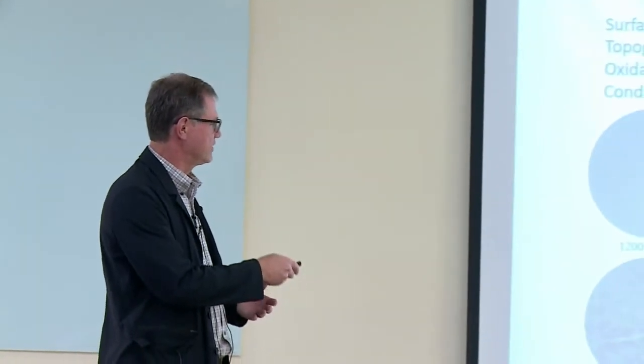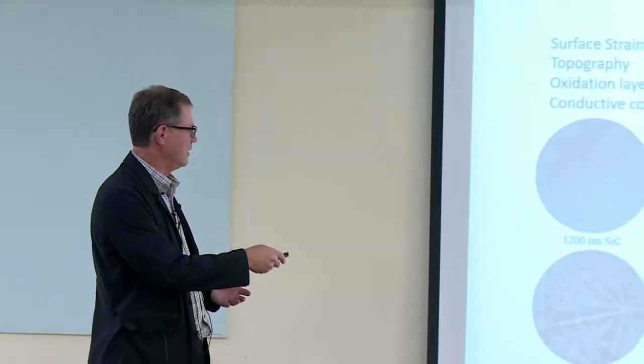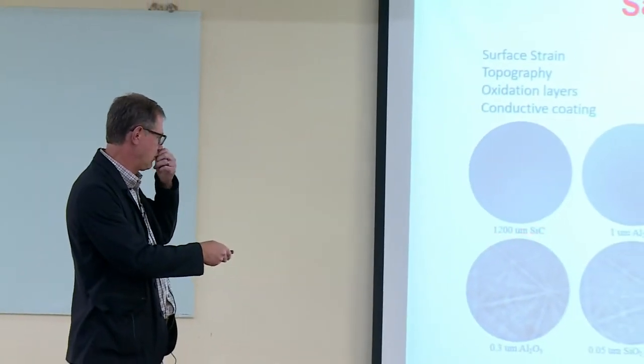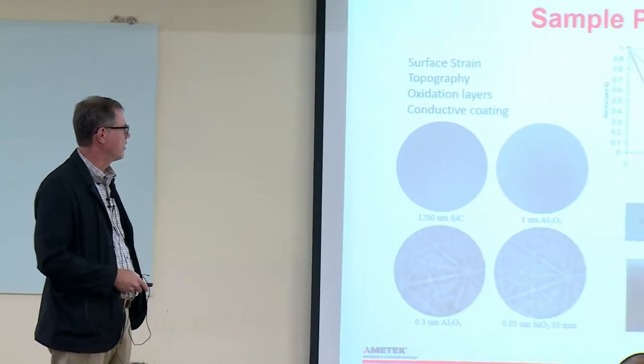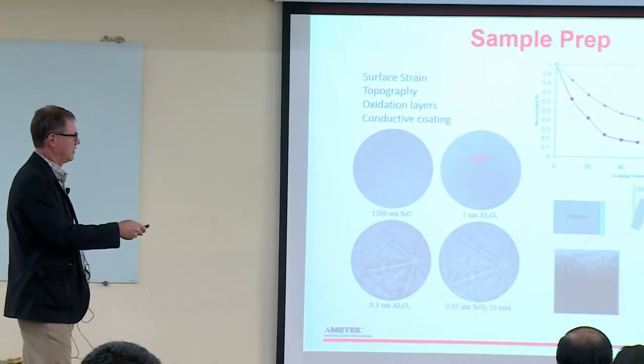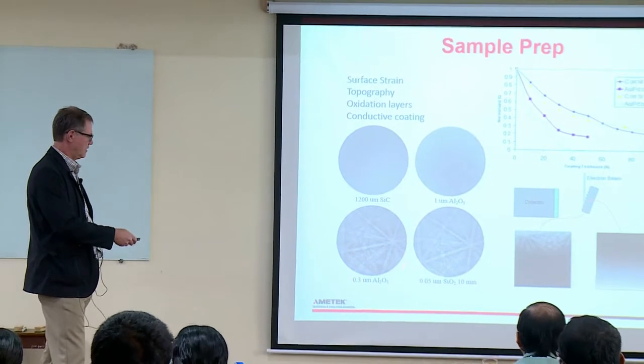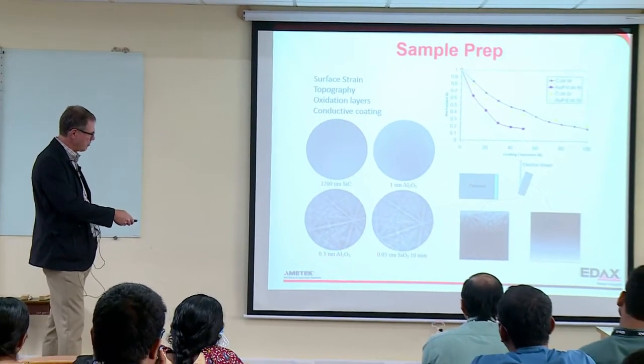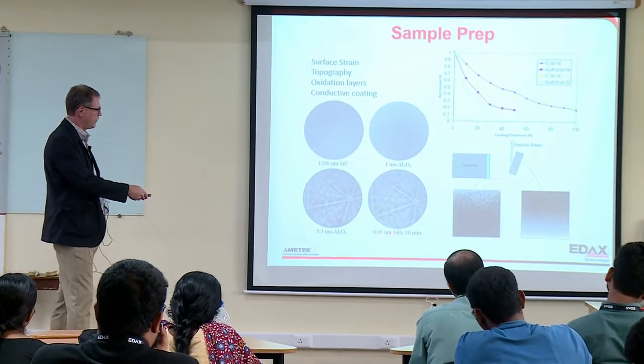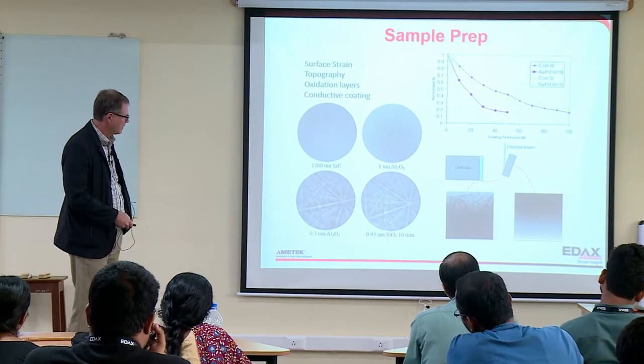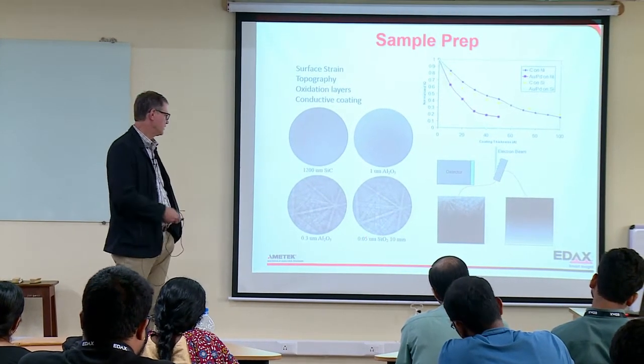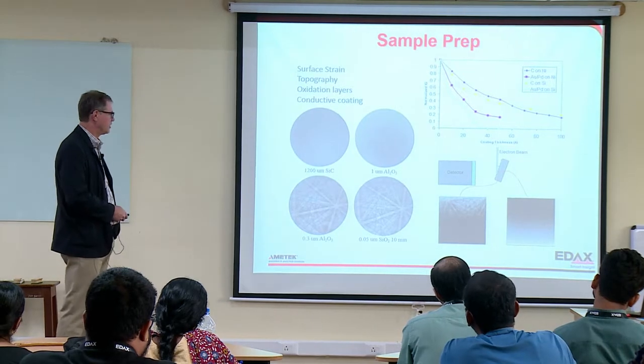And yeah, so this is the kind of pattern you might expect to see if you don't do the sample preparation right. So this is just a quick sequence. This is the material after grinding and polishing to 1200 micron on the silicon carbide papers. And then we did an alumina polish, followed by a 0.3 micron alumina polish, followed by 0.05 microns colloidal silica on a vibratory polisher.